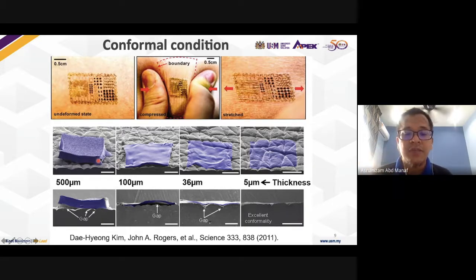If your substrate thickness is 500 micrometers, you can see there is still a gap. The analogy of 500 micrometers is like our silicon wafer thickness, which is about 400 to 700 micrometers. Looking at the image of the skin structures, you can see there is still a gap. It does not really adapt well to the skin. This group then studied 100 micrometers, and there is improvement but still a gap. It cannot follow the conformal structure of the body skin. Then they went to 36 micrometers, with improvement, and after they reduced to 5 micrometers thickness, you can see very good conformity on the skin structures.